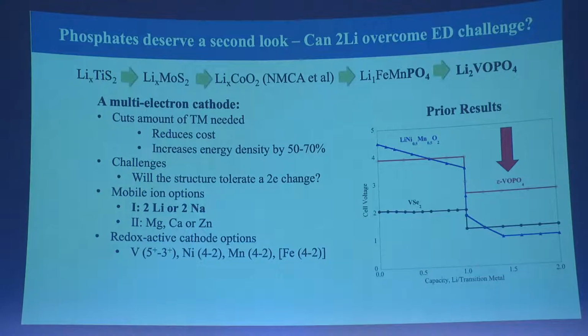Very reversible, no issues at all, except the voltage is too low. Mike Thackeray at Argonne looked at the layered oxides, and again, you can put two lithiums in, but the second lithium's at such a low voltage to be of no interest at all. But what we found out with this vanadium phosphate, VOPO4, and it's the one in the red here, we can put one lithium in at about 4 volts and another one in at 2.5 volts.